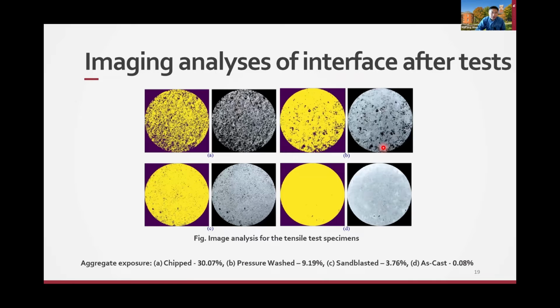And then we wonder, for the interface failure, there can be two typical failure methods. One is the adhesive failure, which means it's happening between the aggregate and the paste. And the second can be cohesive, so it's happening within the paste and the interface. So we use the imaging method to look at how much the aggregate is exposed. That gives us an idea whether it is adhesive failure or cohesive failure.